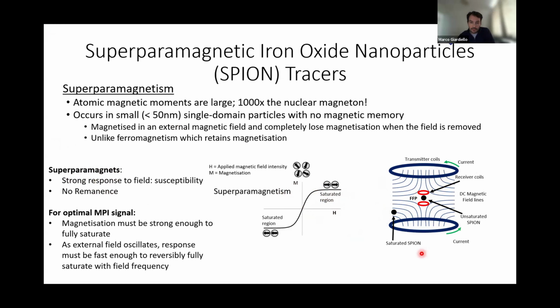You would want to rapidly saturate, so it's in this state, and then rapidly desaturate so that it's not kind of oscillating, you don't split that kind of signal and blur your signal. So you want your magnetization to be strong enough to be fully saturated in the field strength that you have in your scanner, and immediately desaturate in line with the frequency of the oscillating field.